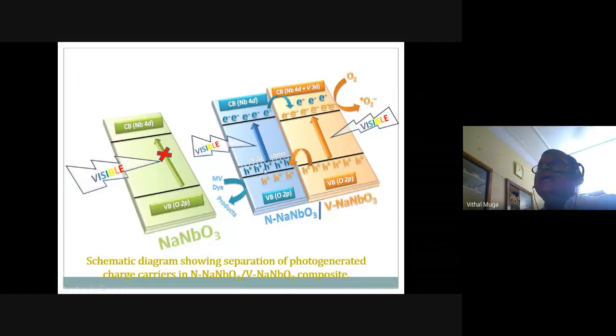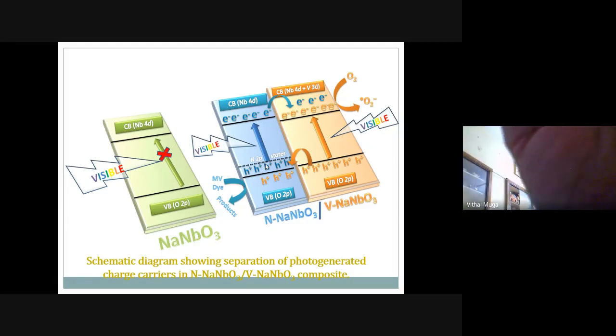Now this is once again the highlight, that we take NaNbO3, then visible light, you cannot get the excitation, it cannot give the photoactivity sufficiently. But when you do N-doped NaNbO3 and V-doped NaNbO3, then it gives a lot of photoactivity, or photoactivity increases enormously. Now, how is it possible? It is possible like this. Once this and this are excited simultaneously, then the electron can go from here to here. Once the electron has gone from here to here, the hole cannot combine with the electron here because it has gone there. Now this actively participates immediately.